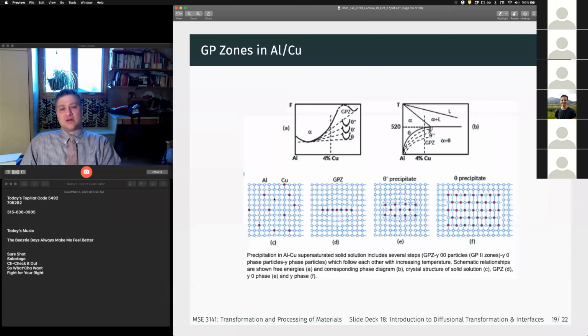Okay, so here's what I was just talking about, right? Our theta phase here has a much larger unit cell, and it forms a fully incoherent interface. But this is our thermodynamically stable phase. This is the lowest energy phase, right? But we can't nucleate this big thing, and we'll talk about why in just a little bit. So instead, we go through a series of intermediate phases, right? First, we form the GP zones that form a fully coherent interface. Then we go to this theta double prime, which is semi-coherent, theta prime, which is also semi-coherent, but a little bit larger. And then the thermodynamically stable theta phase is a fully incoherent particle, right?